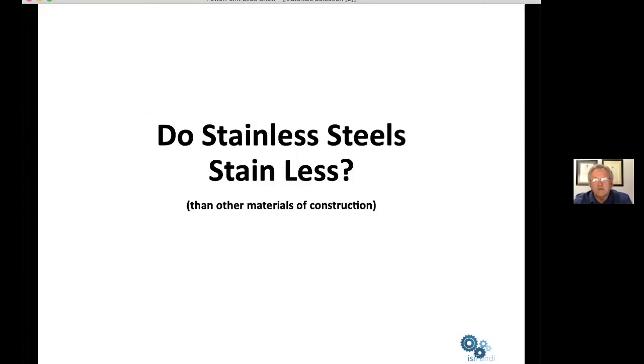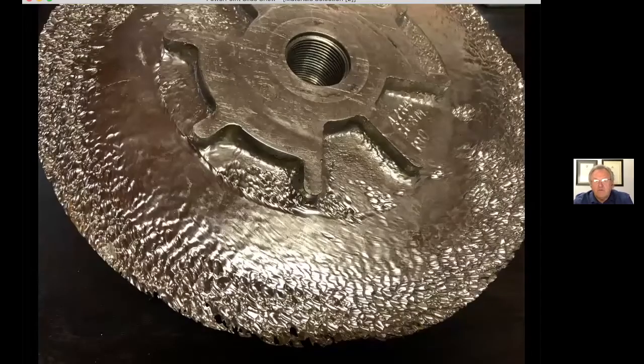Do stainless steels stain less? Here is a photograph of a stainless steel pump impeller. And that pump impeller is still beautifully shiny, and it certainly has stained less. In other words, it hasn't stained at all. But in the environment in which it was used, it actually suffered from catastrophic erosion corrosion. So although stainless steels may stain less, it does not necessarily mean that they corrode less at all times.